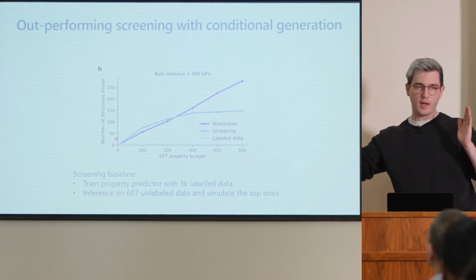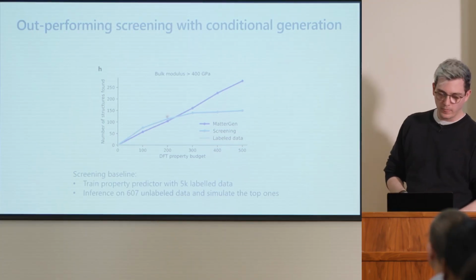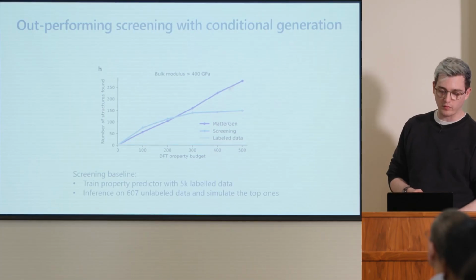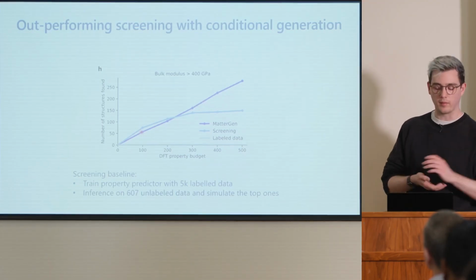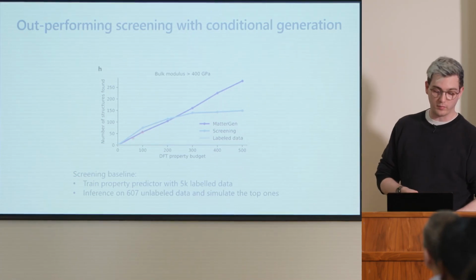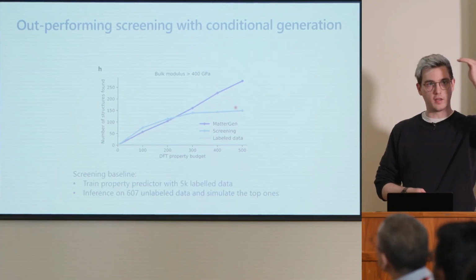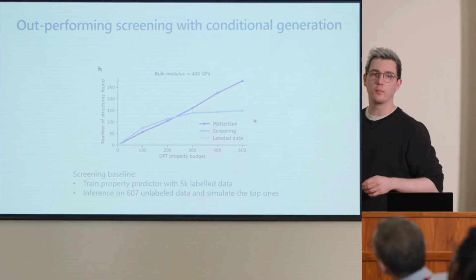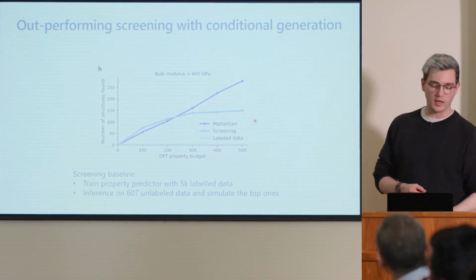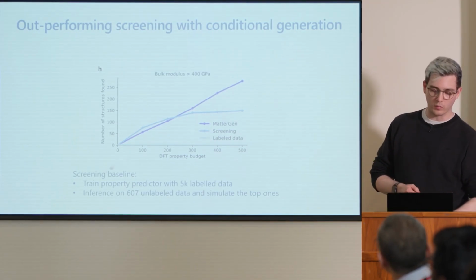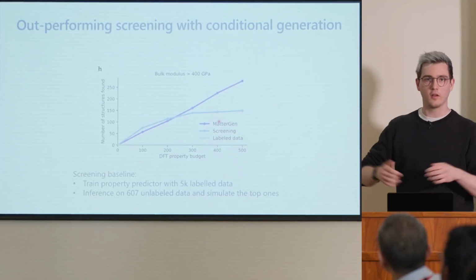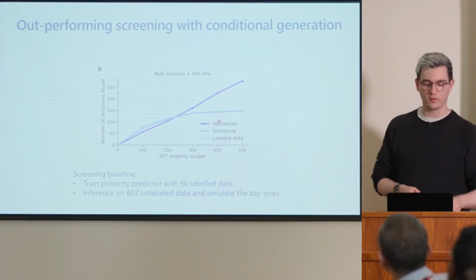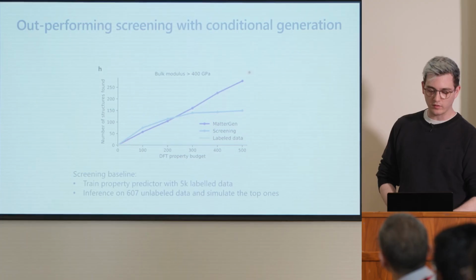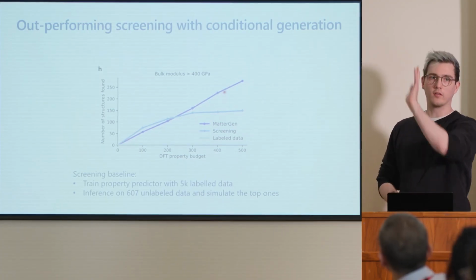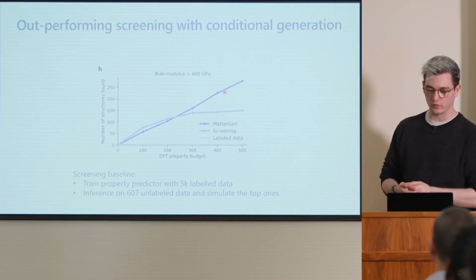So we take the top X predicted values from our data set and check whether they fulfill the constraint of having more than 400 bulk modulus. And that initially works really well because there are some structures in the data set that actually have high bulk modulus. But of course, as you go down the list to less and less promising candidates, this flattens out at some point. At some point, there's just nothing more in your data set that you can add that has this property. On the other hand, with our model, you can just keep generating thousands and thousands of materials with that property constraint in mind, and you can really see that after some time, it overtakes the traditional screening approach and can come up with more proposals.